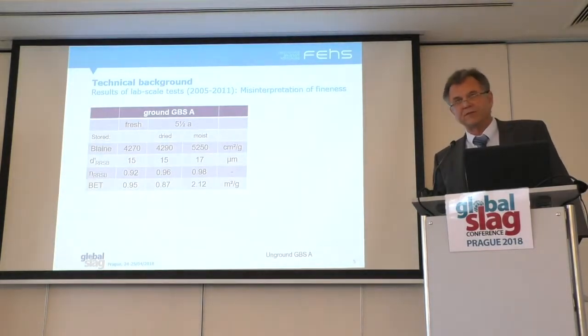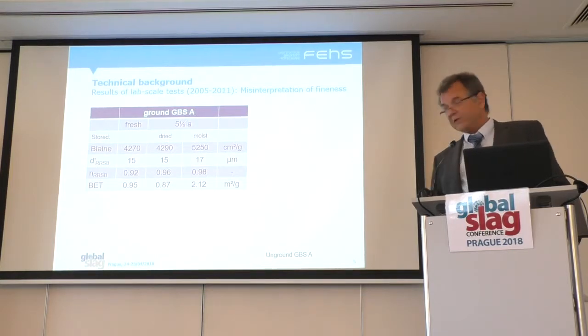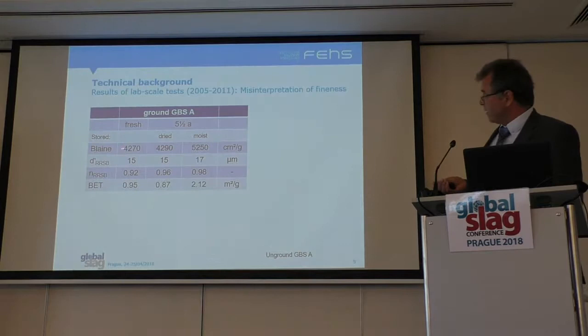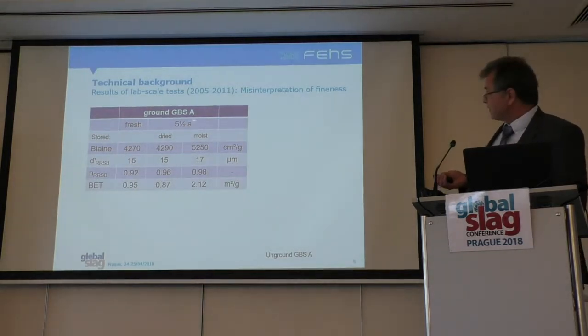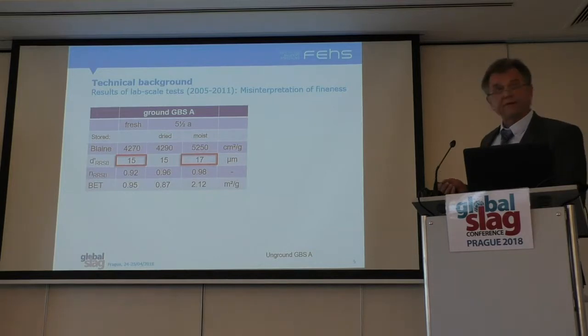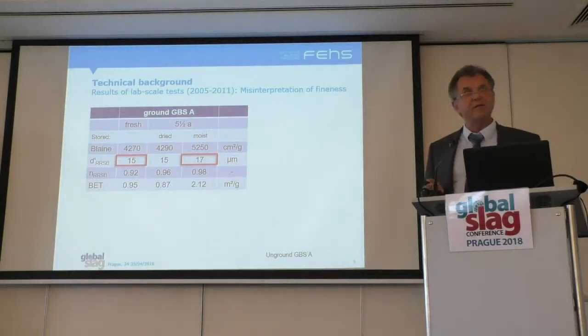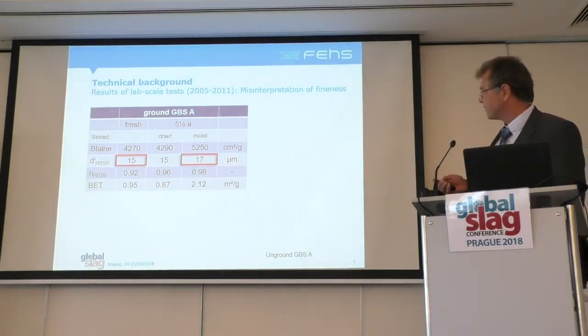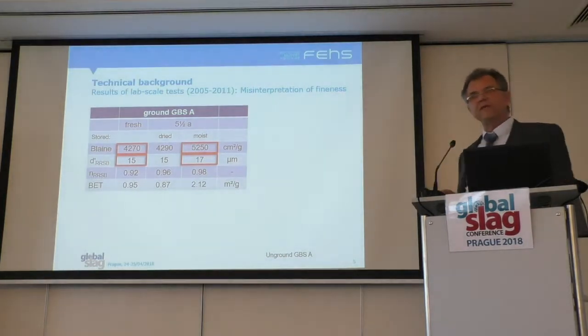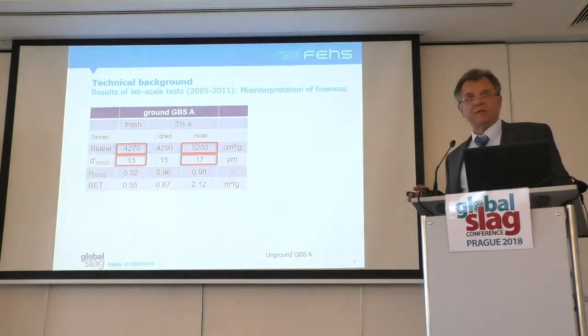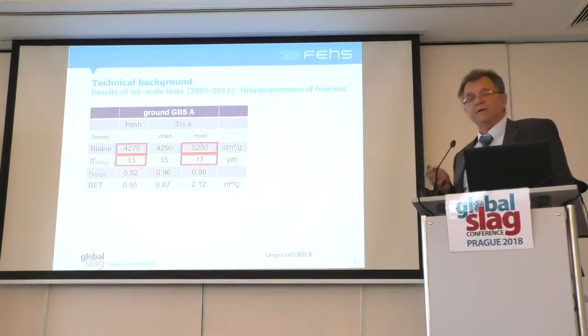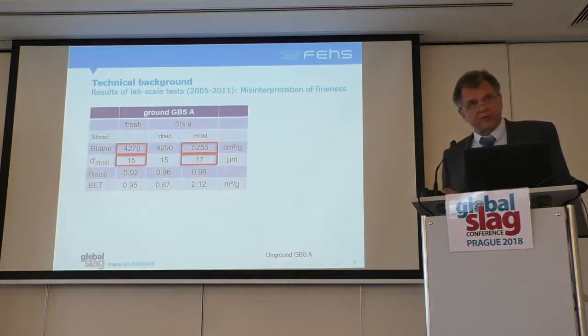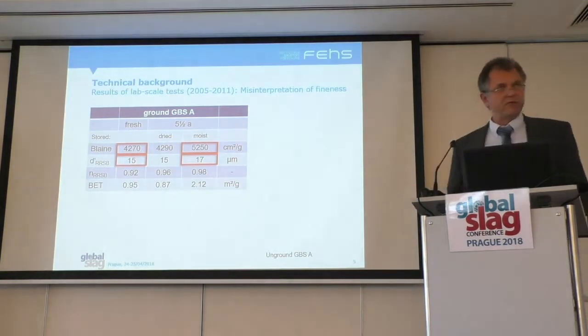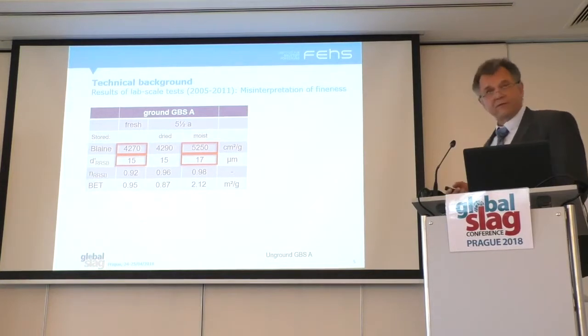The question now is what happens regarding grindability and reactivity of this slag. If you grind this material as we did in our lab, comparing the fresh slag and the stored slag, the dried slag and the moist slag, you will see that if we have the same particle size distribution, which means the same fineness of the powder, you will have at the same time very different Blaine values. And the Blaine value is still a parameter often used in cement production. In reality, you stop your grinding process when you achieve a certain Blaine value, 4000 Blaine for example. In fact, you will have a coarser material.